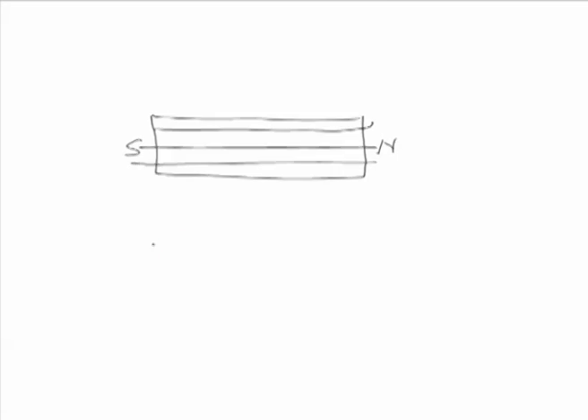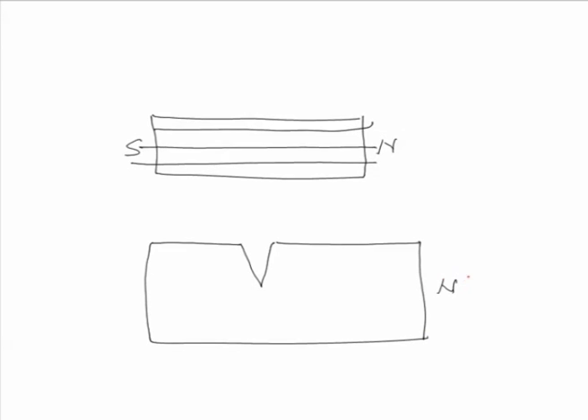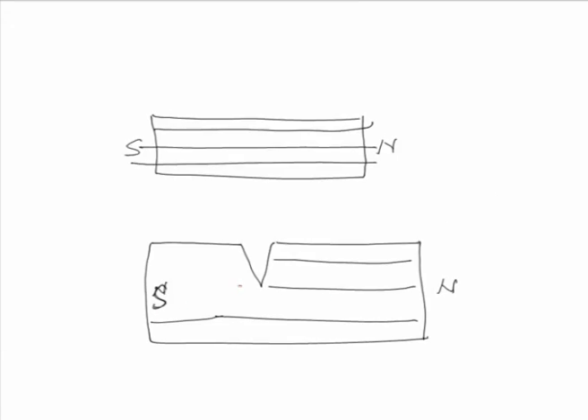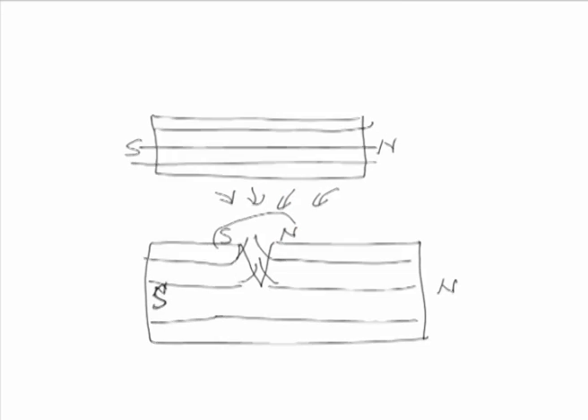And this magnetic particle test works on a very simple principle: a typical magnet has a north and south pole, and the magnetic lines pass through these smoothly. And the moment there is some sort of defect in the component, then in addition to the two poles, wherever the discontinuities are present, leakage of the magnetic flux starts. The leakage will take place wherever discontinuities are present and it will form fresh poles. So, when the powder is sprinkled over the surface, it tends to segregate near the areas where we have discontinuities.